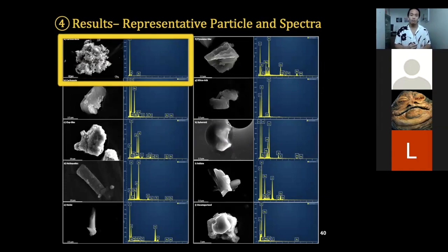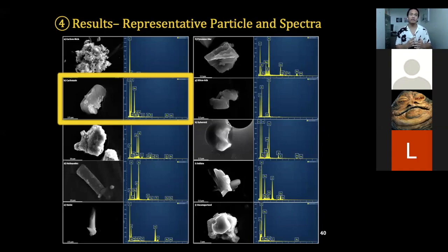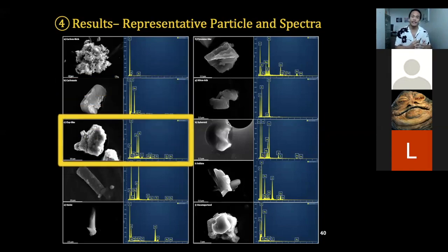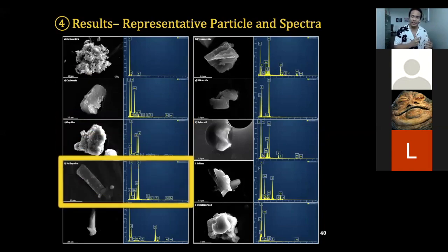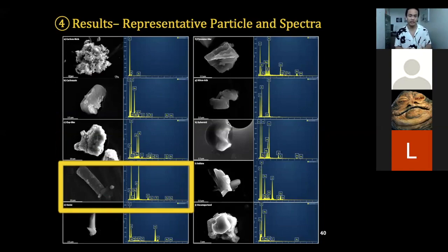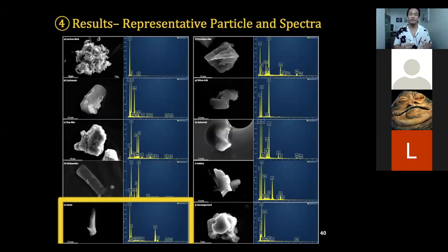Moving down to the carbonate category, we look for particles to have equally high carbon and oxygen peaks in the spectra. And this particular sample also has a high sodium peak. So this is likely a sodium carbonate. The clay-like particles tend to have a flaky or plate-like texture. And then they have a high oxygen peak in the spectra, and then a lot of trace elements also present, probably due to some weathering or alteration. For the feldspathic category, the morphology is varied, and then we looked for spectra that had oxygen, sodium, aluminum, silicon, and potassium. For oxides, we look for particles that have strong oxygen peaks and either a titanium or iron peak.